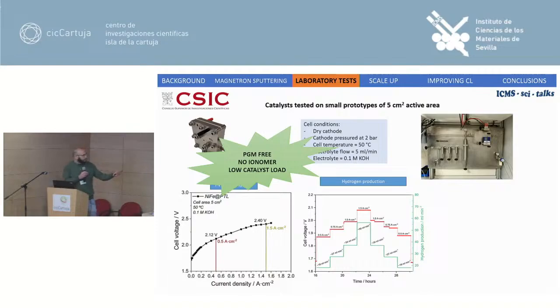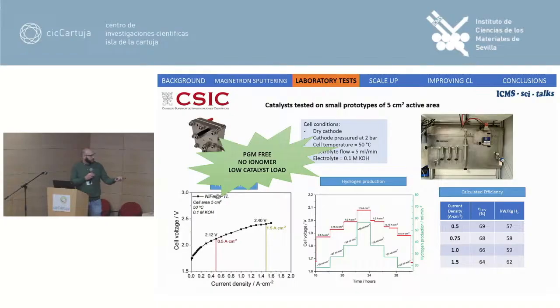Additionally, we were able to measure the amount of hydrogen that we were producing with this prototype, which we are testing in batch in our laboratory. Combining the power density measured in this curve with the amount of hydrogen produced, we can calculate the efficiency of our system, which is more or less around 65% efficiency for the production of hydrogen. This value is more or less the average of other similar systems reported in the literature.